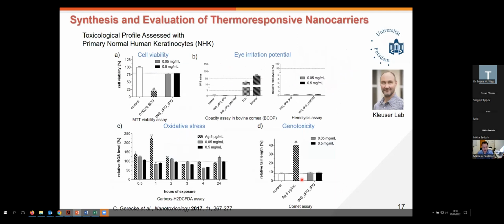Just to finish this first part, before we move to actual biological assays, we have to demonstrate that these materials are biocompatible, at least in preliminary studies. In collaboration with the Kleuser Lab, which was at the University of Potsdam back then, we ran a huge set of experiments analyzing the typical studies of cell viability and cell cytotoxicity. We analyzed as well the irritation potential of the materials. We analyzed if they could exert oxidative stress or any other type of toxicity, like for instance genotoxicity. And in all cases, comparing them against positive and negative controls, we could see that our materials actually have a very interesting biocompatible profile. So this was highly encouraging.